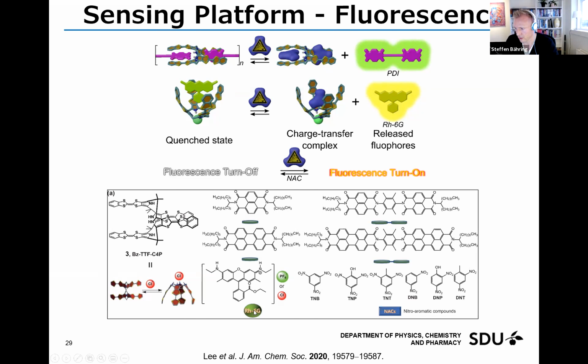Then we also showed that this rhodamine could be applied, where you can see here that it's binding in the cone conformation, and then by introducing explosives which normally bind in the 1,3 alternate conformation, we could also see that some complexation with the explosive took place and the fluorophore was released.